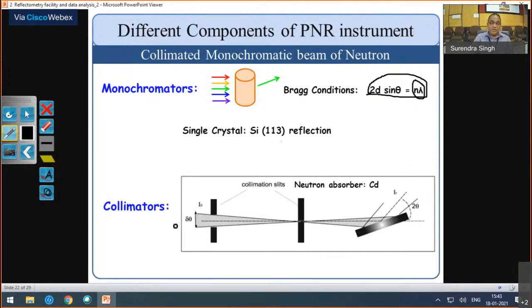Okay, collimator is nothing but two slits, of a different size, neutron absorbing material, and then you get the delta theta from it. And from the monochromator you get delta lambda, because sometimes your crystal is not a perfect crystal, but you have a mosaic spread, because small crystals are randomly oriented. That gives you the delta lambda, and this gives you delta theta. Okay, these two factors are very important in neutron reflectivity. I will explain that. So this is monochromator, this is collimator.